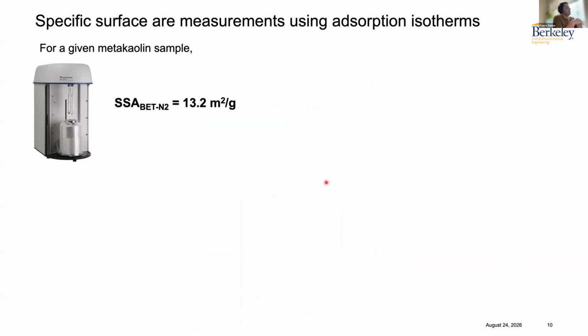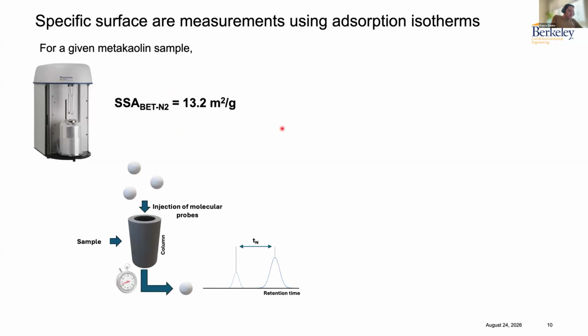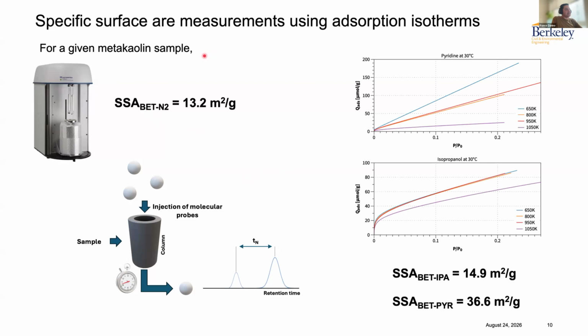So we took this metakaolin, so these are experiments that we did in my lab, and we measured this metakaolin sample. We are not going to go into details on which specific metakaolin, but let's call it material A. And we measured the specific surface area by nitrogen adsorption applying the BET method in the lab as 13.2 square meters per gram. Well, now we have other techniques like inverse gas chromatography that allow us to obtain adsorption isotherms with a bunch of other molecules that are not necessarily nitrogen, as in the typical device that all of us may have in our laboratories. And the interesting thing here, when we try the same metakaolin sample with two new gases, pyridine and isopropanol in this case, is that the surface areas that we obtain can be up to 3 times the value that we obtain by nitrogen.